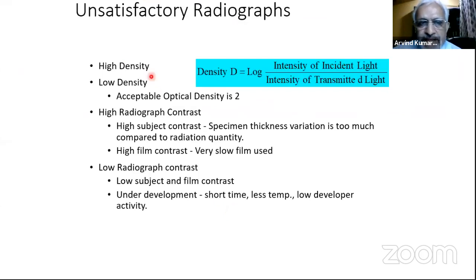Also, your density should be okay. Generally, since we're talking about what the code says, I'm talking about the same code again, ASME. For gamma radiography, the density required is 2 to 4. You can accept a minimum of 2 and a maximum of 4 as a density. Whereas for X-ray, you can accept 1.8 to 4. With X-ray, you can go slightly on the lower side also. It gives better sensitivity. So 1.8 to 4 is acceptable.